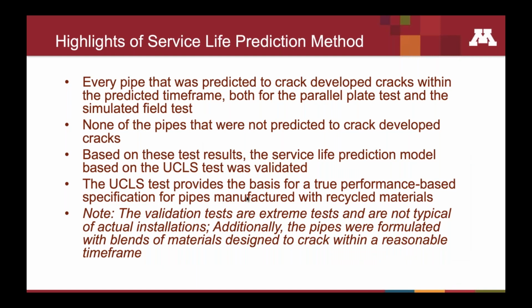So again, every pipe that was predicted to crack did. Those that were not predicted to crack did not. And basically, the beauty of this is that this has given us our first, what we call a performance-based standard for these products. Prior to this, there was never a performance-based standard for pipe materials, and now we actually have that. So that was very, very exciting. Note also that these are validation tests, and they're very extreme. They're not typical of actual installations, and the pipes were formulated with blends of materials designed to crack within a reasonable time frame.